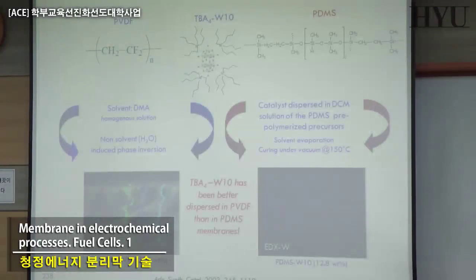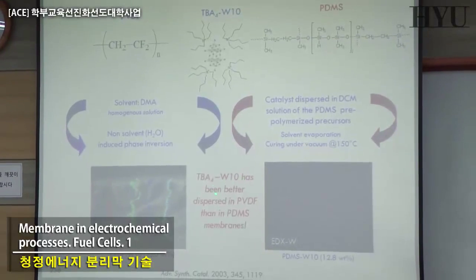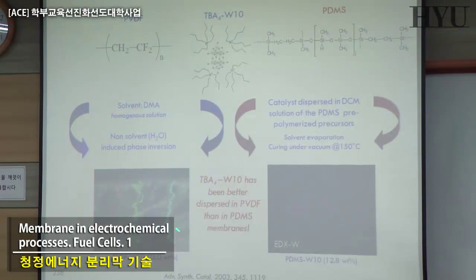At the end, it has performance very different from the one that is dispersed in PVDF. The TBA W10 is much better dispersed in PVDF than in PDMS. This dispersion is important to control the reaction, to avoid the clustering of the catalyst in the polymer. Having a homogeneous distribution as much as possible in the system is very important. In these two cases, you see in one case it was working, in the other one it was not working. The dispersion was much worse in one of the polymers, which is a very traditional polymer that everybody is using, a rubbery polymer for making membranes, for gas separation, etc. So this one, forget. Very good membranes, but not appropriate for immobilizing this kind of catalyst for sure.